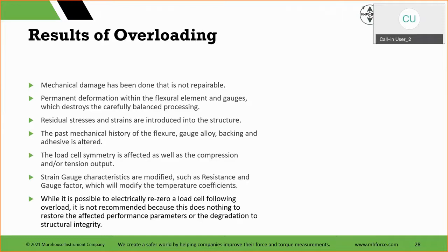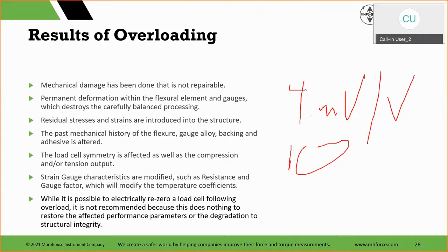The past mechanical history of the flexure, gauge alloy, and adhesive is altered. The load cell symmetry is affected, as well as compression and/or tension output. And when we say symmetry, that's compression and tension, which means, hey, if prior to my overload my load cell was reading 4 millivolts per volt, or you can go, hey, it was reading 10, let's say that equates to 10,000. Sorry for my scribble here, I'm using my mouse. Say that equates to 10,000 pounds.